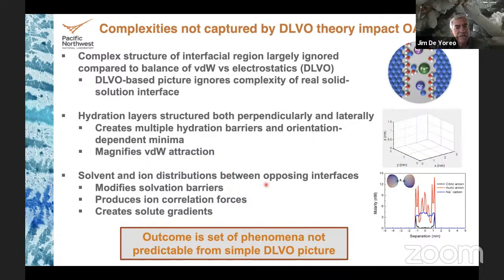And then there are solvent and ion distributions between the opposing interfaces that are impacted by the existence of those interfaces and the solvent structuring. Those in themselves, so this is a plot, this is a calculated plot, this is not data, showing a distribution of ions between two surfaces. Those modify the solvation barriers, they produce their own ion correlation forces, and they create solute gradients that can alter the chemical potential in the system. So the outcome is a set of phenomena that's just not predictable from simple DLVO theory. The question is, how do we get to a quantitative picture of growth of nanocrystals by oriented attachment?